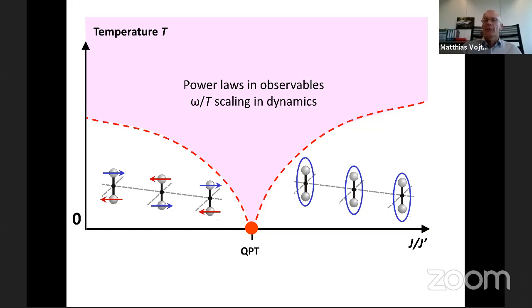The exact models which people have considered, most of them are actually for spin 1/2, but a few are also for larger spin. The bottom line of all of this is spin liquids can exist for higher spin. For instance, we know that the Kitaev model for spin 1, which works very similarly to the Kitaev model for spin 1/2, is no longer exactly solvable, but it features a spin liquid phase, which is a Z2 spin liquid. So that's known. Numerics is good enough to say this. There is also some work on the Kagome lattice Heisenberg antiferromagnet with spin 1, and there are indications that this also has a spin liquid regime somewhere in the phase diagram.